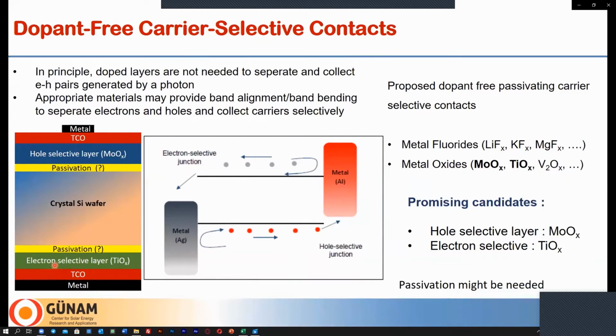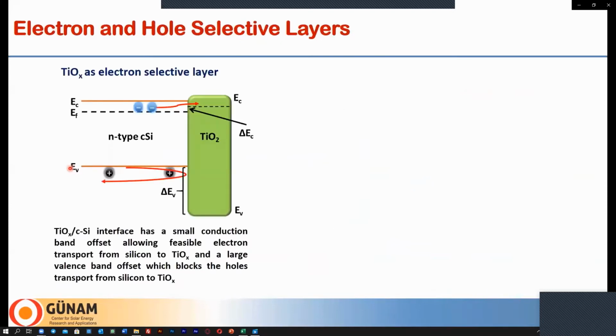And this material can be placed, for example, this is the hole collecting layer placed at the front side. This is the electron collecting layer, which is on the back side. In some cases, especially for molybdenum oxide, you might need some passivation layer. So if we look closer at titanium dioxide, we see that titanium dioxide forms a small conduction band offset, so electrons can tunnel and reach the contact, while there is a large valence band offset, so holes are reflected